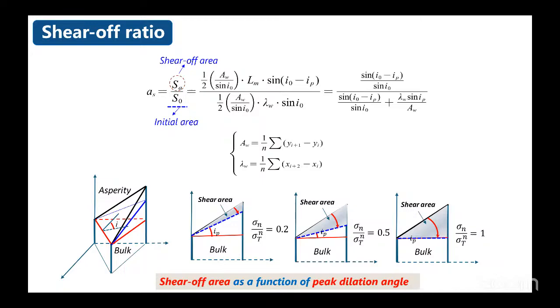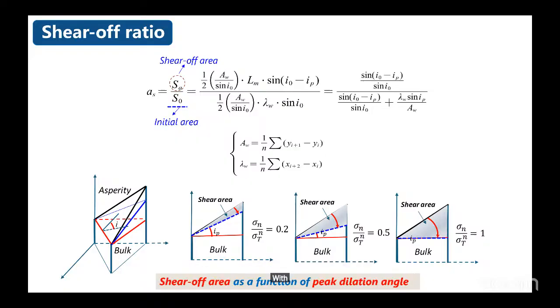Once the peak dilation angle and the truly sheared asperities are determined, we can compute the shear-off ratio. That is the ratio between the shear-off area of each asperity and the initial asperity area facing the shear direction. We found that the shear-off ratio is only related to the geometrical properties, including the asperity slope, amplitude, and wavelength, and the peak dilation angle. The geometrical properties can be easily measured by 3D surface digitization and reconstruction technology.